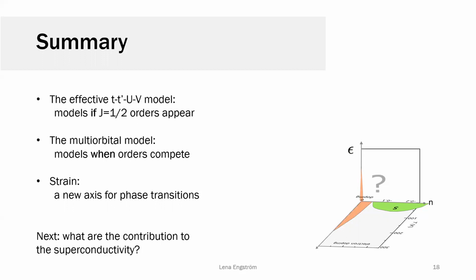Okay, so I'll go. You mentioned how the superconducting dome, this little dome here in green, shows up as the antiferromagnetic order diminishes. But with the strain, you showed how you get this metallic phase. So would you expect there to be a difference in the type of superconductivity you get when you have this intermediate metallic phase versus when you come straight out of the antiferromagnet?